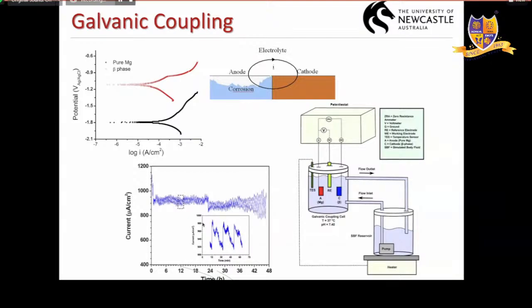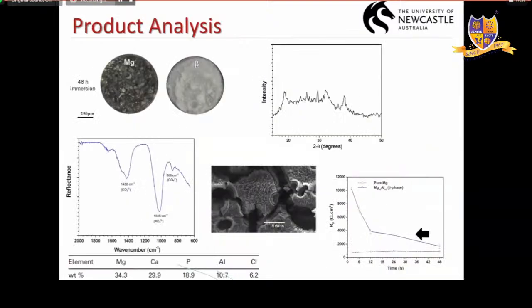Interestingly, it was not a smooth curve, right? You see a cyclic pattern of high current and low current. A closer observation of those samples revealed that there were bubbles forming on the samples. On one side the magnesium slowly dissolves, and on the other side there are bubbles forming on top of the beta phase particles. We took that to analysis using SEM, and as you can see, magnesium dissolution was uniform. It was pure magnesium, by the way, and this was the beta phase. On the beta phase, we didn't expect it to dissolve, but it formed a product on top of that. Analysis of the product using FTIR and EDX showed that it's an amorphous phase composed of calcium and phosphate,